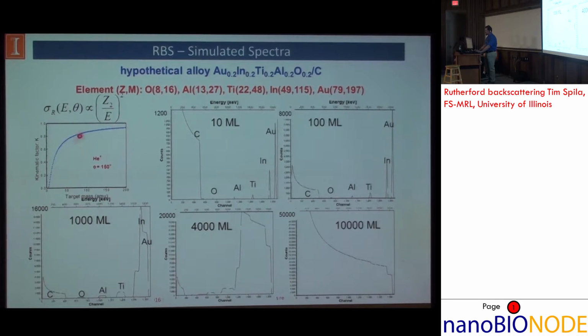So I'll remind you of our shape here. So what do we got? We have 10 monolayers of our film, and we can see we have a lot of counts for gold, less for indium, less for titanium, aluminum, and oxygen. So we can see we have much higher sensitivity for the higher Z materials.